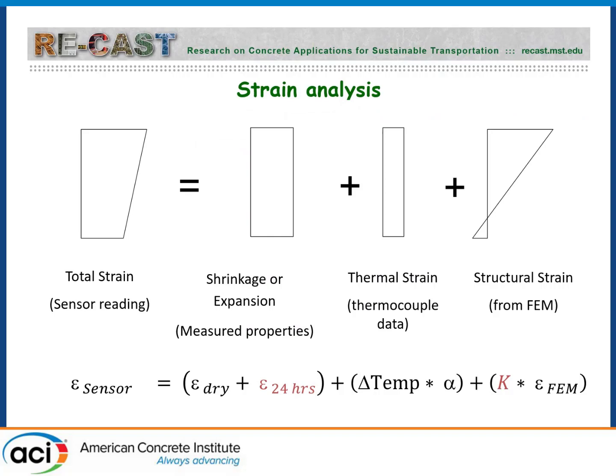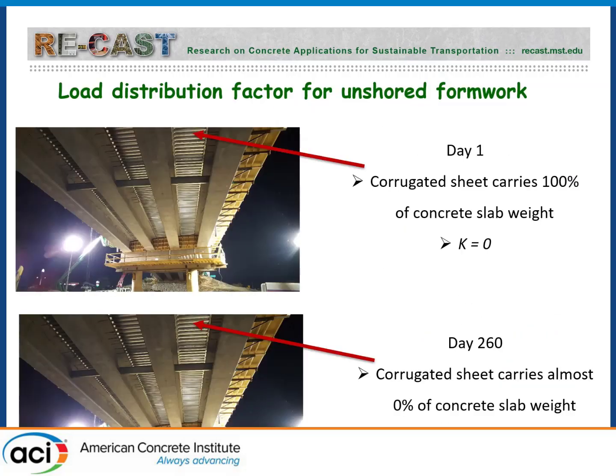So as I said, we also did some finite element analysis, and I don't have a lot of time to go through this, but briefly, we wanted to know what is the autogenous shrinkage after 1 day, because our prisms were demolded after 1 day. There was already some chemical shrinkage, some self-desiccation. So we wanted to know that, and we also wanted to know how much load was being carried by the corrugated steel. When you cast the concrete on the corrugated steel, you don't expect anything to be supported by the girders. So indeed, it was zero.